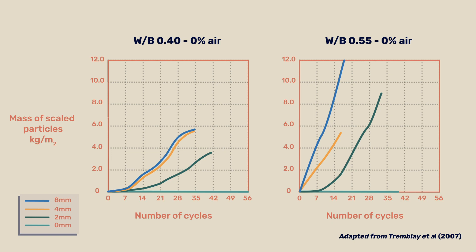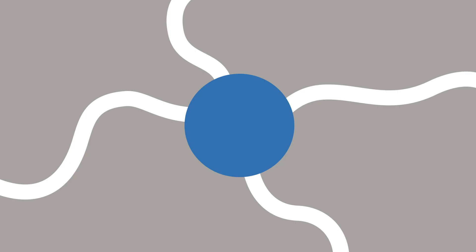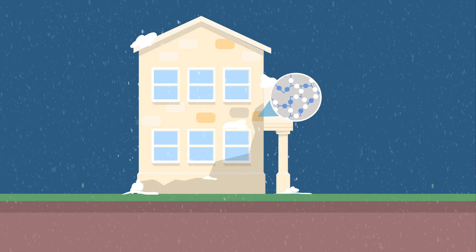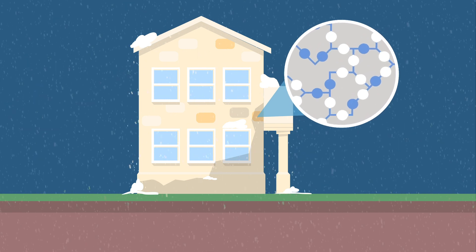Damage is exacerbated in concrete prepared with a high water-to-binder ratio, which leads to lower tensile strength and higher porosity. Surface damage can result from abrasion, bursting of water-filled air voids as they freeze, or crystallization pressure in pores near the surface.